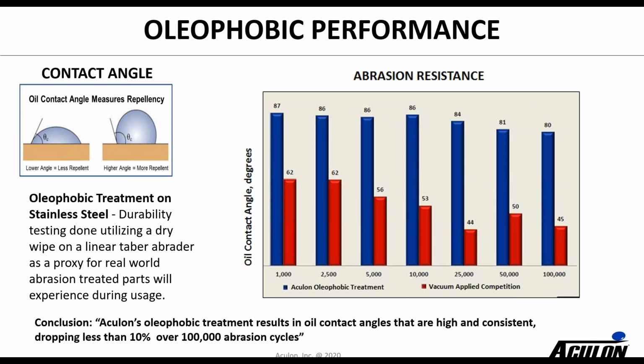What we do is treat the stainless steel with the dry wipe. We put it on a linear taber abrader and abrade it. You can see up to 100,000 cycles. During that time frame, we're measuring the oil contact angle. You can see in blue, this is an example of one of our oleophobic treatments we use on metal. Even after 100,000 abrasion cycles, it starts at 87 degrees contact angle and goes down to 80 degrees. So very stable, good oleophobic performance.